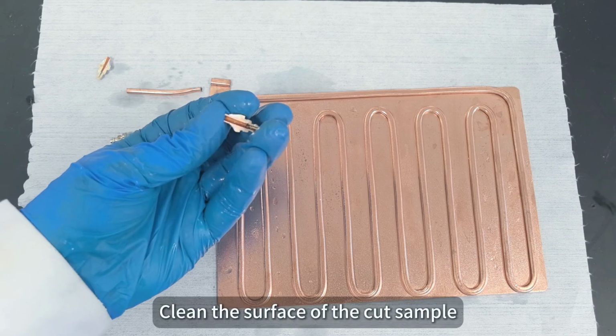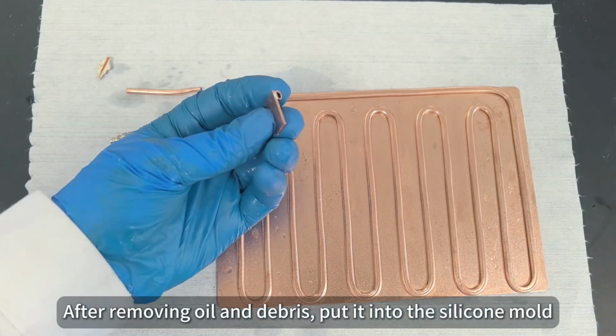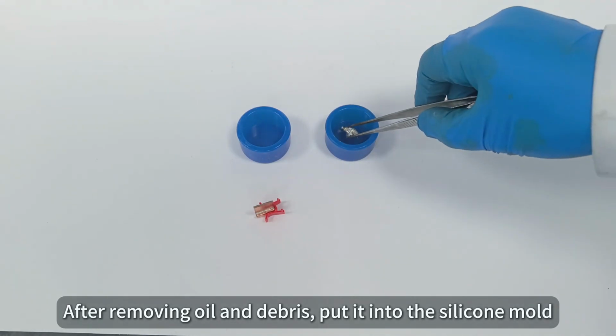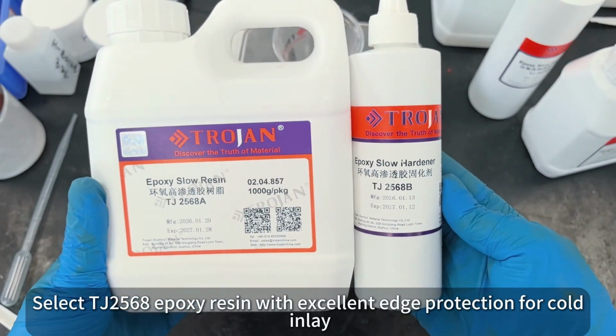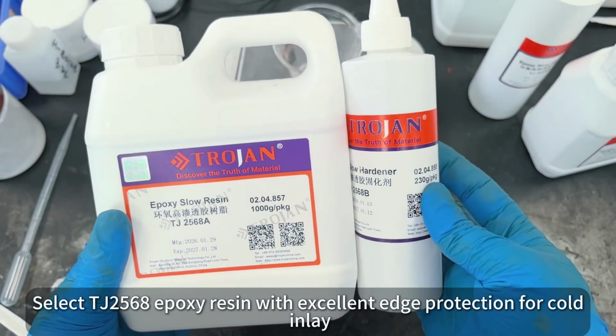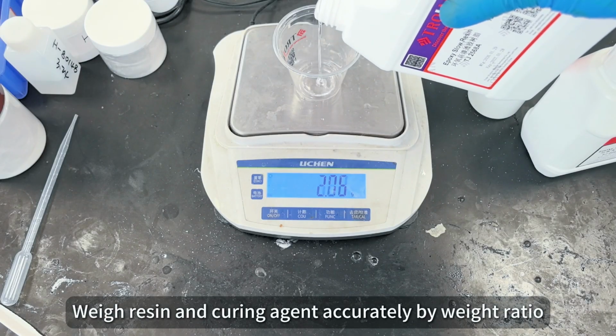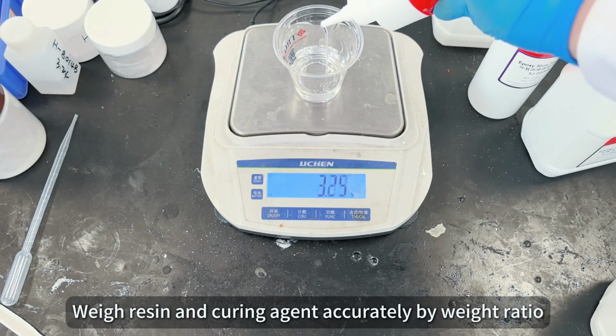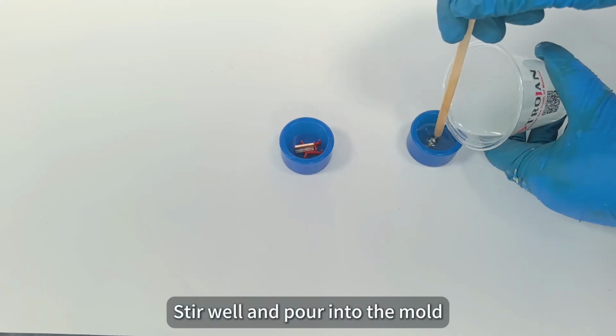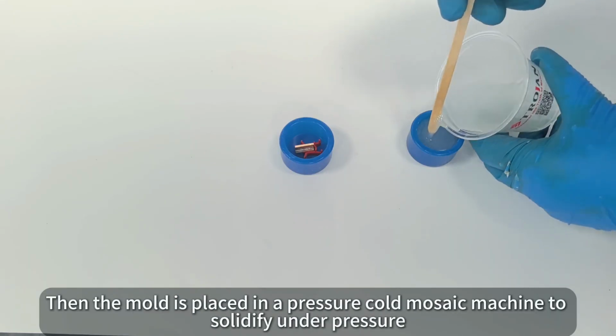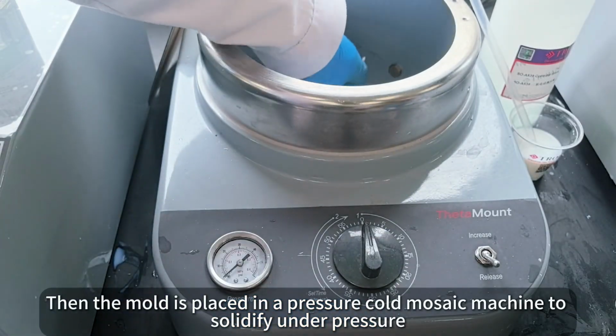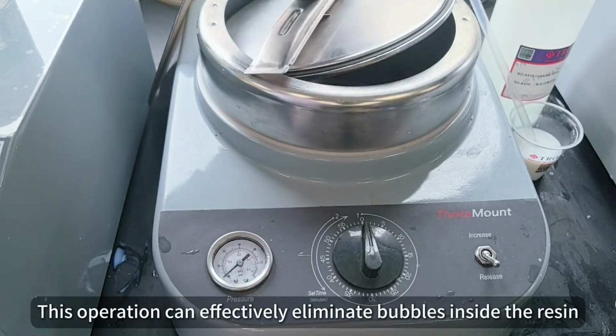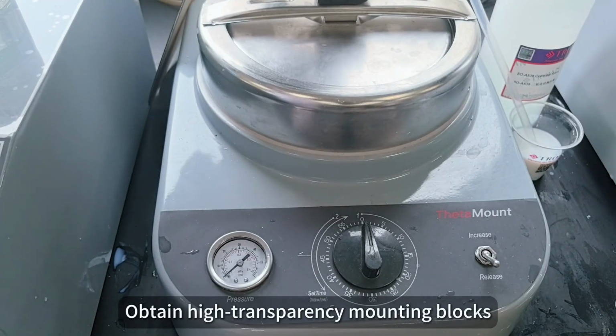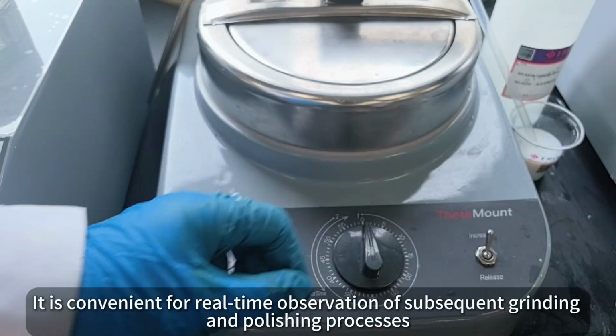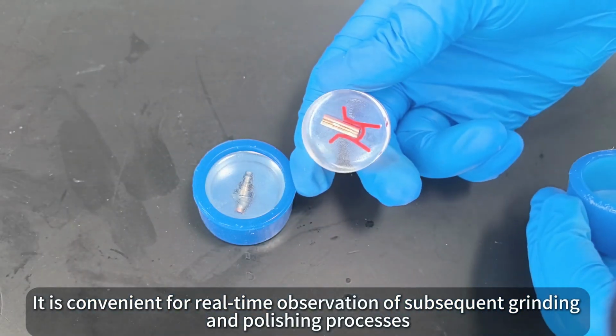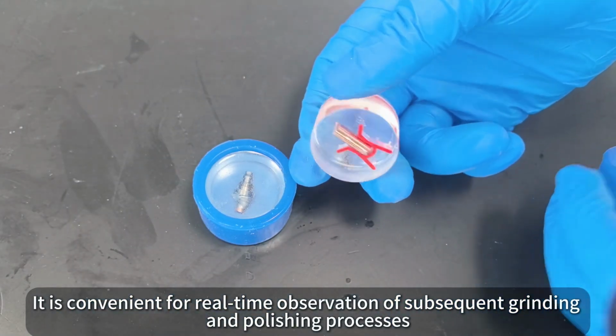Mounting. Clean the surface of the cut sample. After removing oil and debris, put it into the silicone mold. Select TJ2568 epoxy resin with excellent edge protection for cold inlay. Weigh the resin and curing agent accurately by weight ratio. Stir well and pour into the mold. Then the mold is placed in a pressure cold mounting machine to solidify under pressure. This operation can effectively eliminate bubbles inside the resin, giving high-transparency mounting blocks. It is convenient for real-time observation of the subsequent grinding and polishing processes.